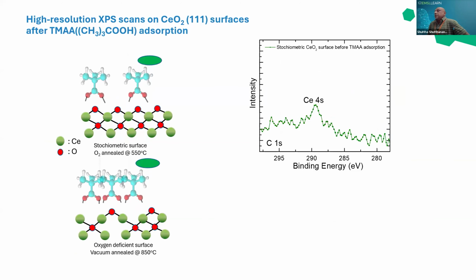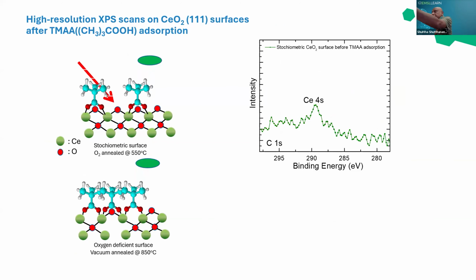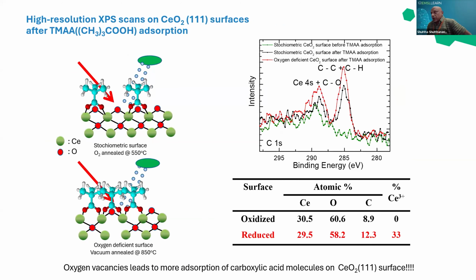Okay. So here we are again putting these carboxylic acids on these two different surfaces. Initially, the green one is a bare surface, and there is nothing deposited. Then when we deposited the carboxylic acid, you can clearly see a peak started coming at 285 eV binding energy, which belongs to carbon-carbon or carbon-hydrogen bonding.